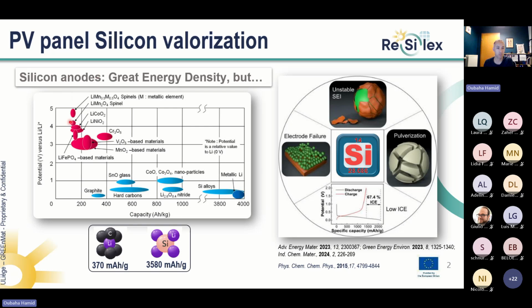Actually, the reaction between lithium and silicon has been known since the 70s, and one silicon atom can react with 4 lithium atoms. This leads to a high capacity, more or less 10 times that of the commercially available and used graphite, where one lithium needs 6 atoms of carbon to be stored. Another property of silicon is that the silicon alloy, when it reacts with lithium, has a relatively low potential, which leads to high energy density.